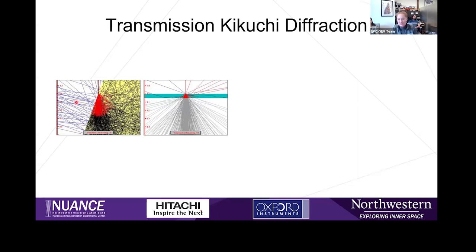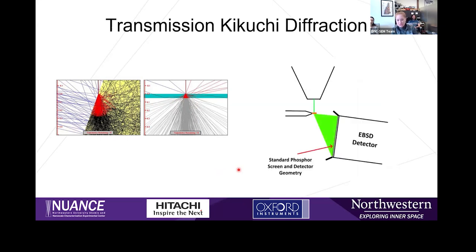Because of that, your spatial resolution is relatively low in traditional EBSD, whereas if you do things like TEM and use a very thin sample, you can see that the interaction is very small, and so you increase your spatial resolution. So you can do high resolution EBSD by doing transmission Kikuchi diffraction. In transmission Kikuchi diffraction, the beam passes through a thin sample and the diffracted electrons are projected onto the phosphor screen. In this geometry, you can see it's not right on axis. It has to diffract into the detector still, but in this geometry, it's still very powerful, very useful.